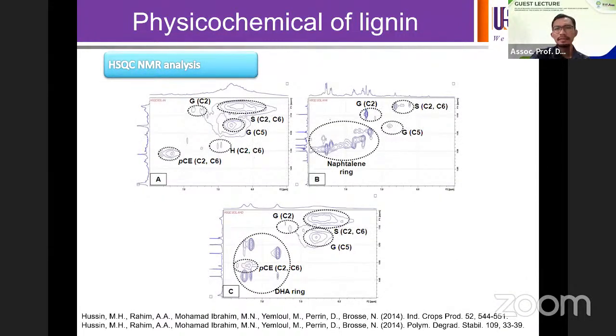We also did an advanced technique like two-dimensional NMR, in this case HSQC, heteronuclear single quantum coherence. We just want to see the clustering of organic scavengers rather than the presence of lignin. So without modification, you wouldn't see any presence of naphthalene ring or dihydroxyanthraquinone. You just see the presence of the main monomers of lignin. But after the modification, you can see the presence of naphthalene ring and also dihydroxyanthraquinone.